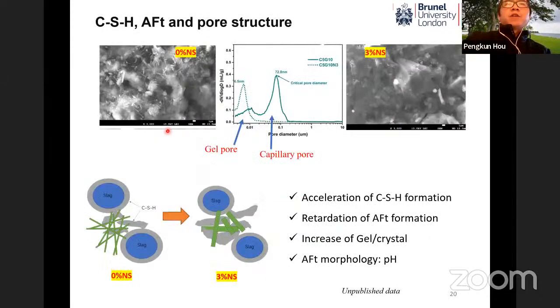So actually, these kinds of features can be more easily found from the SEM image. You can see from here, without nanosilica, it's very porous, with fine crystals, needles, which is the ettringite, and a lot of pores, of course. Actually, these are capillary pores. But with the addition of 3% of nanosilica, we can see that the structure can be greatly densified. And then you can see the critical pore diameter shifted from 72 nanometers to about 6.5 nanometers, which is actually the gel pores.